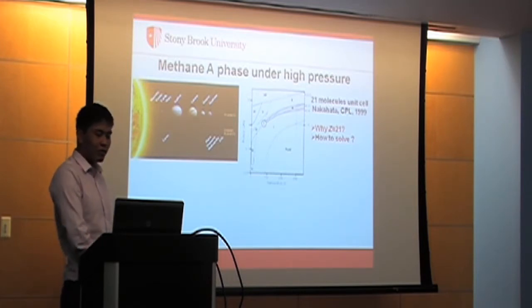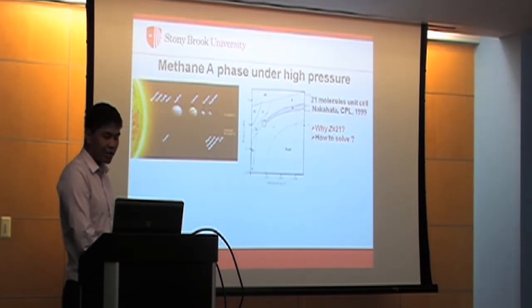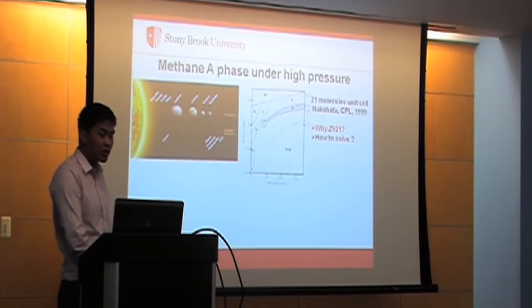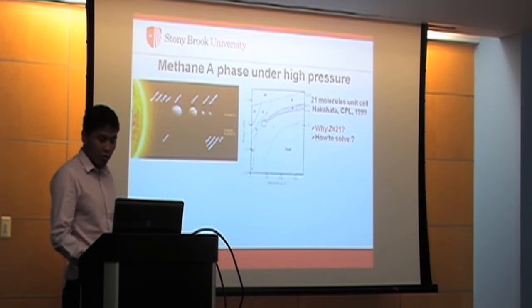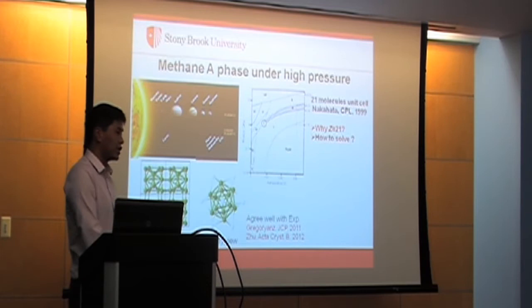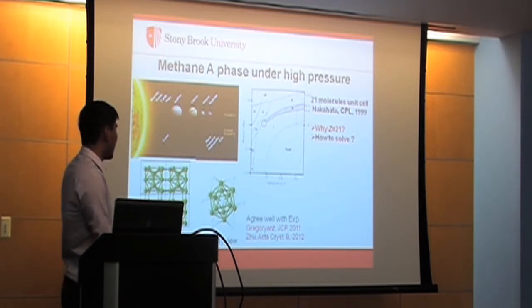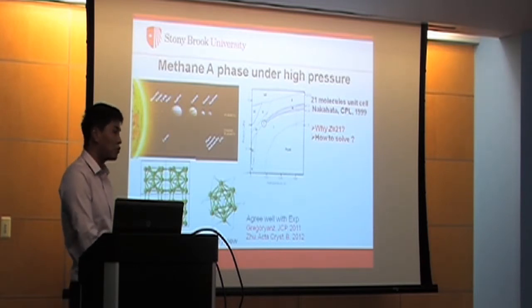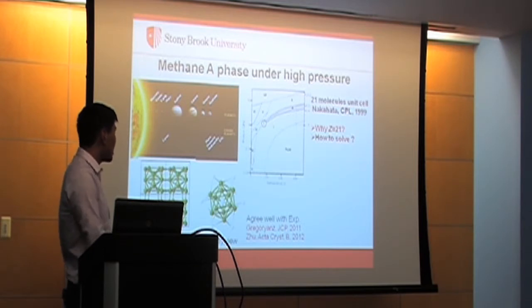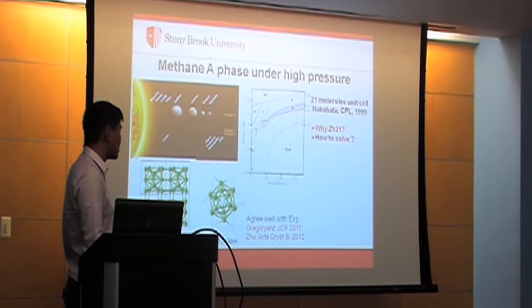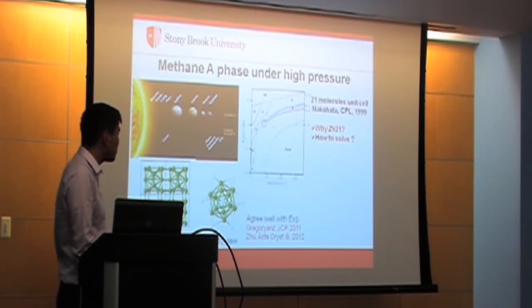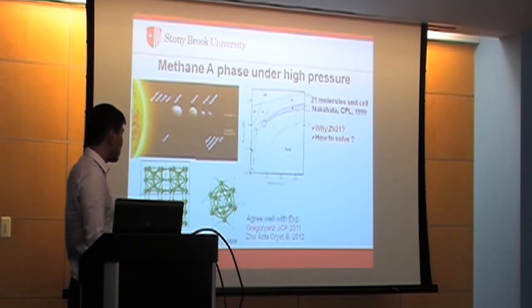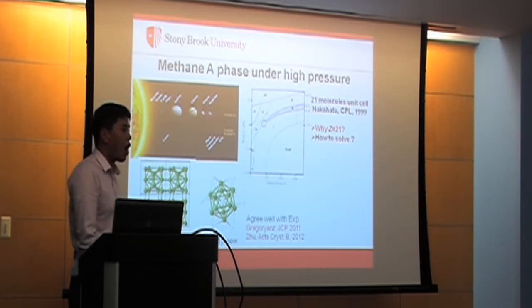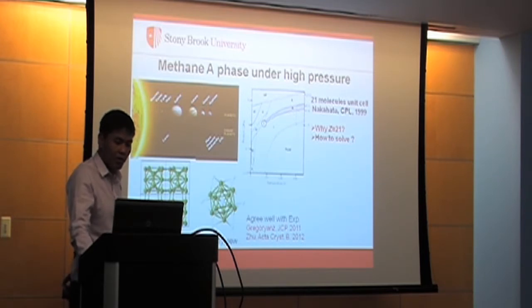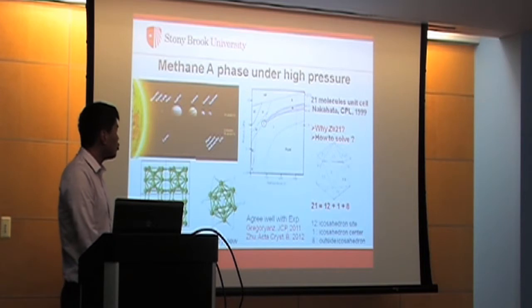Solving the exact crystal structure requires a substantial amount of effort from both experiment and theory. But we tried our method. Surprisingly, within just one day, we found very low energy structures, and when we compared these structures with the experimental results, we found they match very well. And during the period of our work, another experimental group published a high quality neutron diffraction pattern and proposed a structure based on this pattern, and we found that this structure is exactly what we saw in our evolutionary search.